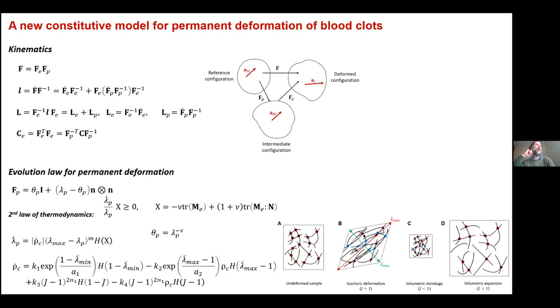So a stent is made from metal, and the reason metal deforms permanently is because of dislocation glide in the microstructure. Any material scientist in the audience will know about this. Of course, we don't have dislocations in a blood clot, but what we do have is the fiber network, which is lots of crosslinks. And we've proposed a new model, which we submitted to the special issue, where we say